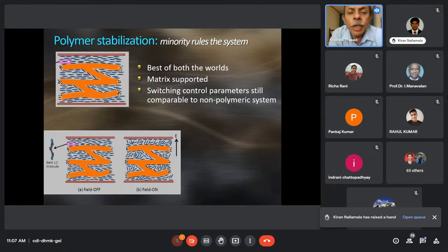So can we now look at the opposite part of the spectrum, wherein the liquid crystal forms a majority and the polymer is a minor component? That's what people have been studying as polymer stabilized systems. In these, the content of the polymer is only a few percent of the total system, and the liquid crystal dominates as far as the content of the system. But what people found early on is that PDLCs are mechanically rigid, whereas the liquid crystal alone, since it's a liquid, is not a freestanding or self-supporting system. But now can we combine the best of both worlds?